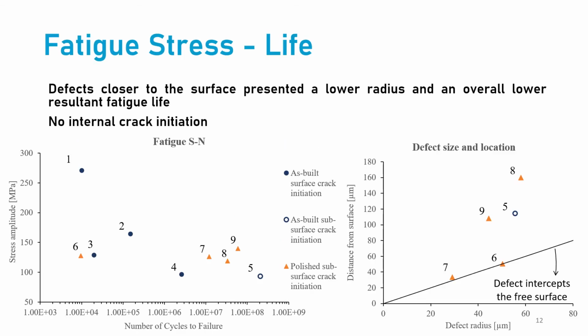On the contrary to the as-built specimens, which showed predominantly crack initiation at the surface, polished specimens proved a subsurface crack initiation in all fatigue tests. No internal crack initiation was observed in either as-built or polished specimens.